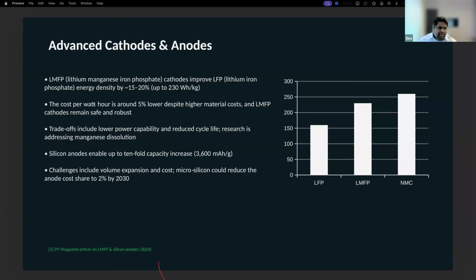Partial replacement of graphite with around 5 to 15% silicon is currently being looked at by researchers as a way of maintaining mechanical stability, while high silicon anodes use conductive binders and flexible matrices. So different percentages of silicon are being tried for different applications of the batteries, and that's being actively researched at the moment. Pre-lithiation techniques add lithium to the anode to offset the initial loss of lithium due to the formation of the solid electrolyte interface, boosting the capacity.